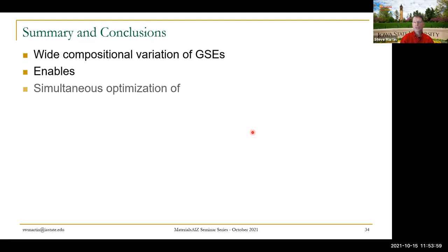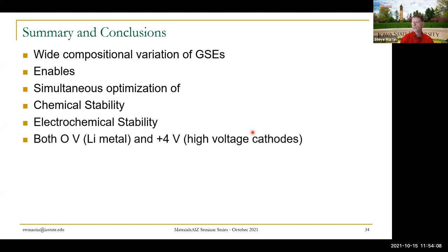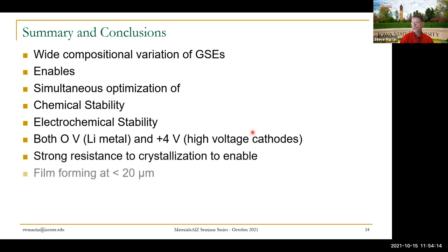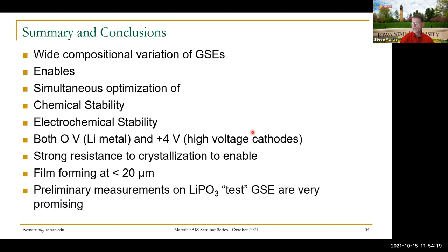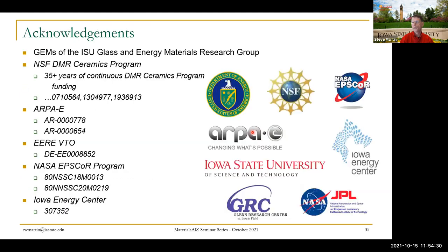This wide compositional variation of these glassy solid electrolytes enables a simultaneous optimization of the fundamental properties: chemical stability, electrochemical stability, and then oxidation and reduction stability. And then also strong resistance to crystallization. We've demonstrated how we can form that at 20 microns. And what I've reported on today, and I hope to report on in the future, is this lithium metaphosphate test glass that looks very, very promising in terms of our technique.